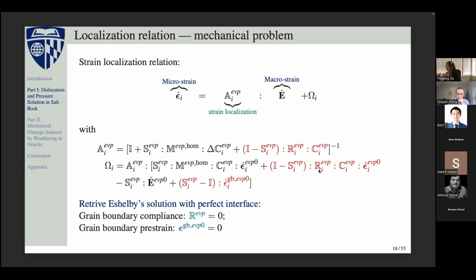So we have these fundamental equations. This one is derived from the Eshelby-based equation that I just mentioned, and it's quite complicated, but overall it's a linear relationship that can relate the microstrain to the macrostrain rate. Here A is a fourth-order tensor, a so-called strain localization tensor, and it contains information of both the solid part, the void part, and also the grain interface part. So it can definitely give us information on how to simulate the pressure solution mechanism and the dislocation mechanism.